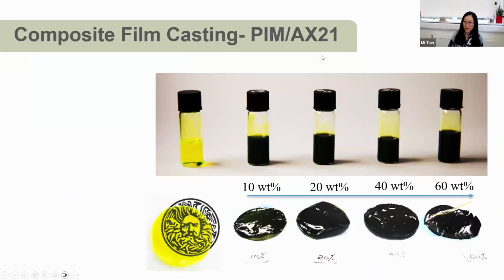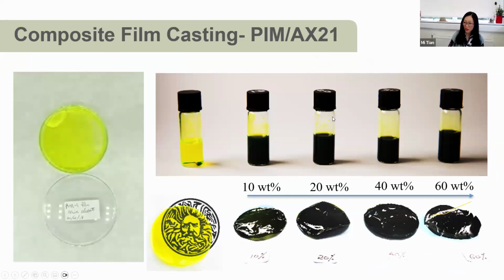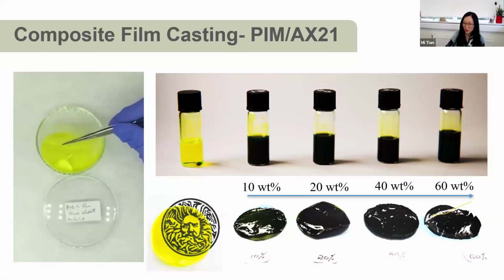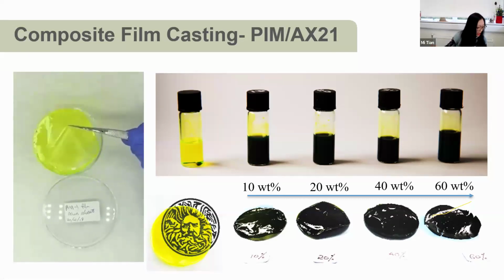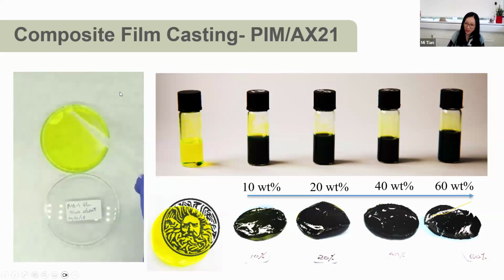So these are composite membranes we fabricated. We dissolve the PIM1 powder granules into DMF, and then we mix with different porous fillers at different concentration. Then we cast it into a petri dish. Then when everything is drying out, we can lift the freestanding robust film up, just like the video shows here.